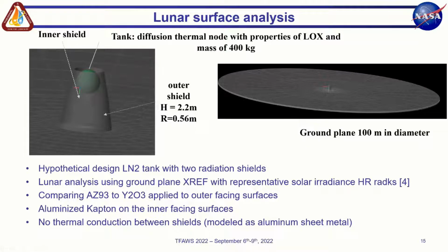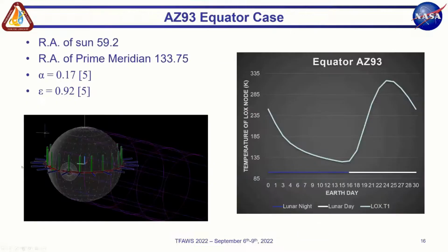And all we did here was take either AZ93, which is more of a standard reflective coating, and compare it to this yttrium oxide material, at least using its laboratory measurements. So maybe a spray coating might be slightly different. Another drawback to mention is we only had data from 0 to 25 microns. So I assumed out beyond that, because some of the energy is beyond 25 microns. We assumed it had a greater emissivity further out, and I think the cutoff was 500 microns for this model. So that's about it for this slide. Next slide there.